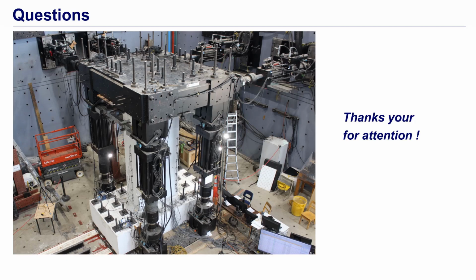Okay. Here's one. Could you use vibrators or vibrating forms to eliminate the voids in the UHPC joints? Well, yes, you can, but you have to be cautious not to over vibrate it. So usually, if you have a good mix design, it can flow, and you let it flow. However, it happened in our lab that the UHPC may become a bit too sticky, too viscous, so the viscosity is a bit too high.